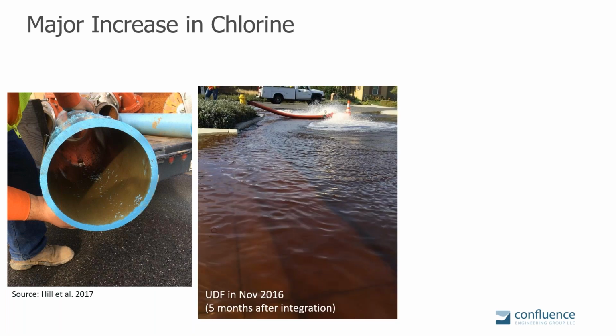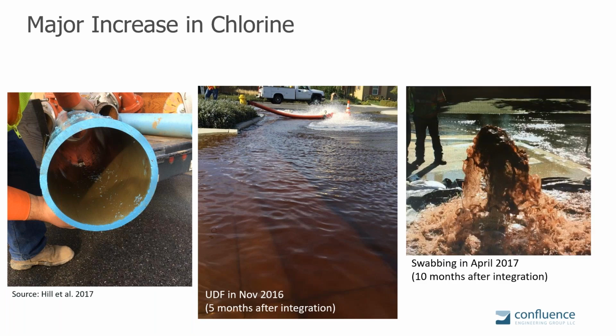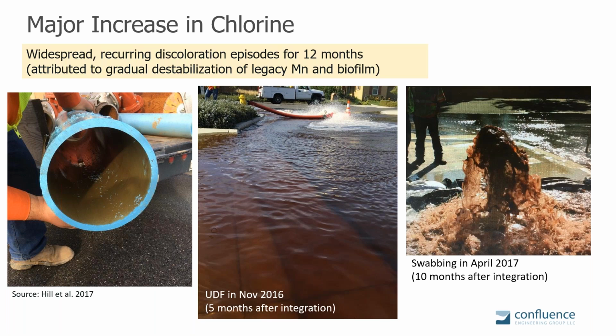destabilized this material, and flushing, even coming back after 2 weeks, after 5 weeks, this tea-colored material from this ongoing destabilization of the pipe materials from the chlorine was occurring, and flushing was just not enough to get it out. Eventually they had to do swabbing 10 months later, and this is still the amount of material that was coming off of pipes that looked like this, with very thin films. So in this case, there was a widespread recurring discoloration episode that lasted for about 12 months. So this is a chemical destabilization. And that was attributed to destabilization of the legacy manganese and biofilm adhered to this pipe due to the introduction, a major increase in chlorine.